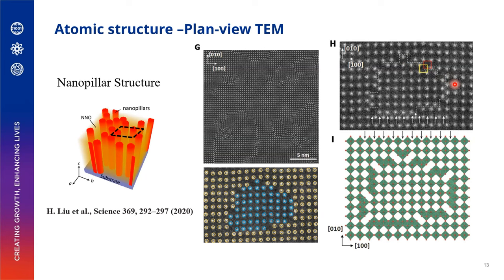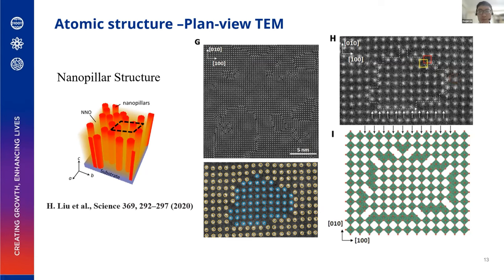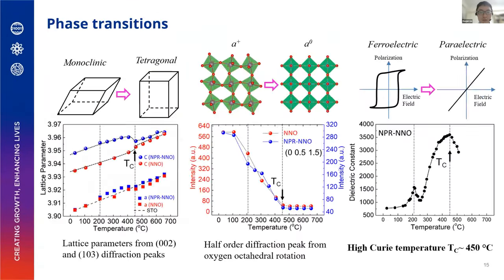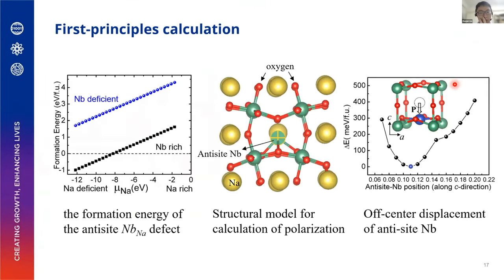Okay, and you can tune the size of these things by changing composition. Yes, that's what we did in last year's Nature Communications work. This one is potassium sodium niobate, but I think the concept is the same. You reduce the A site concentration, and basically you can introduce a higher density of the boundaries. Okay. And then that gives you a stronger response.